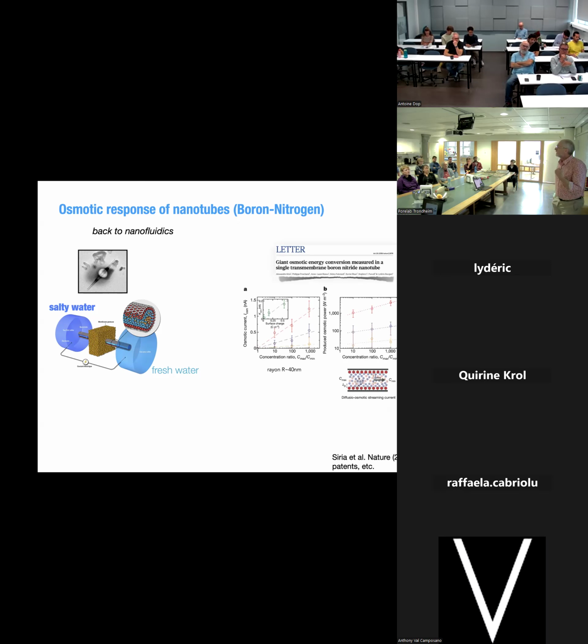And indeed, you measure an ionic current. For a single boron nitride nanotube, it was in the nanoampere range. Nanoampere is very small, of course, but if we do the same with a pressure drop of 1 bar, we get picoampere. So for us, it was very large when we saw that. Of course, this is corrected for the Nernst potential and so on. But that was very surprising.